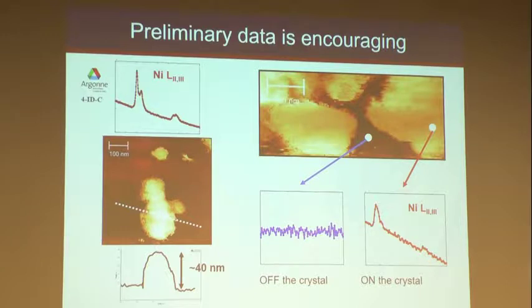And the data on the right is basically showing that we can tell where the particle is by imaging at a spot where you don't see morphologically a particle and you don't get any nickel signal. And if you're in the sample, you can get a nickel spectrum. Now we can take these nickel spectra and interpret them based on whether it could be nickel 2, nickel 3, or nickel 4. And that will tell us what the surface of that electrode, or the near surface of that electrode, in what state it is.